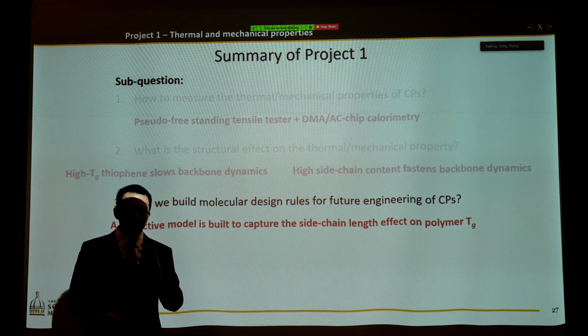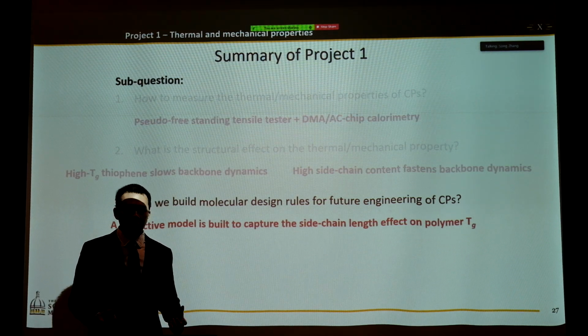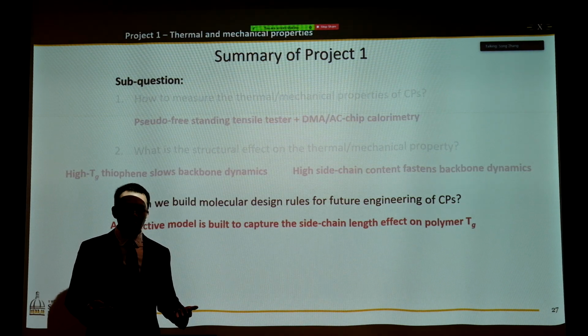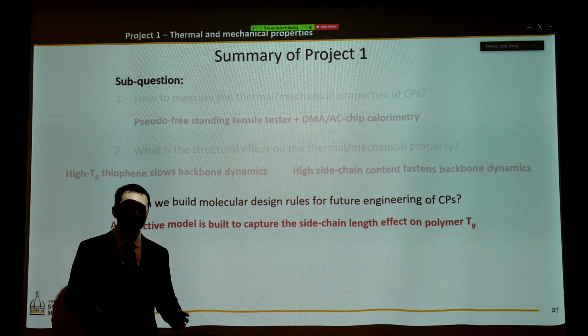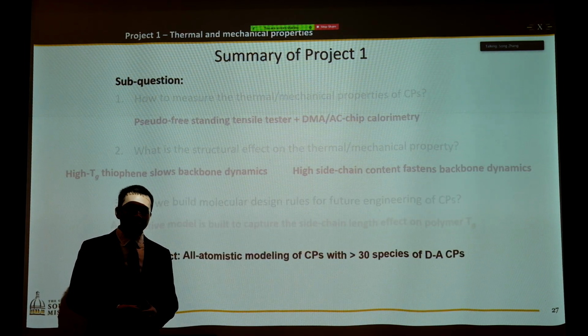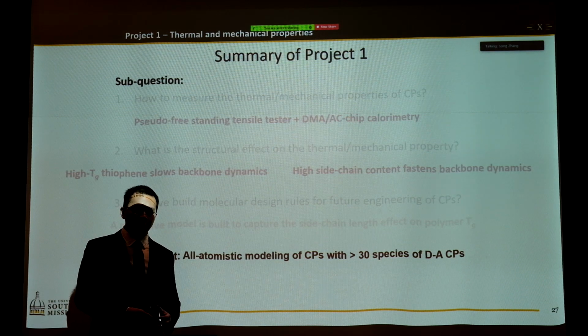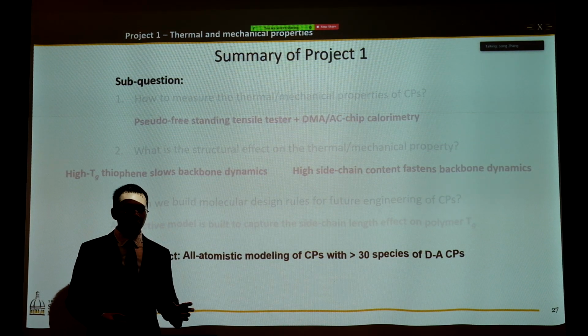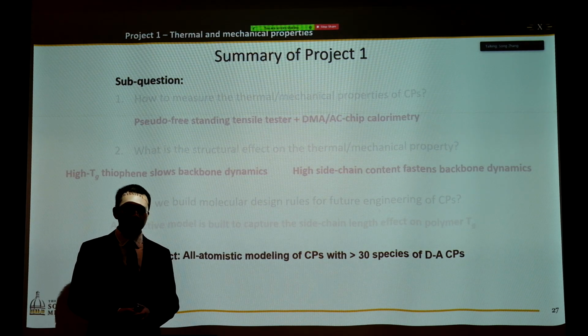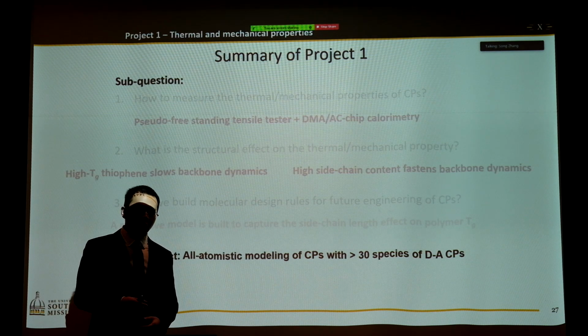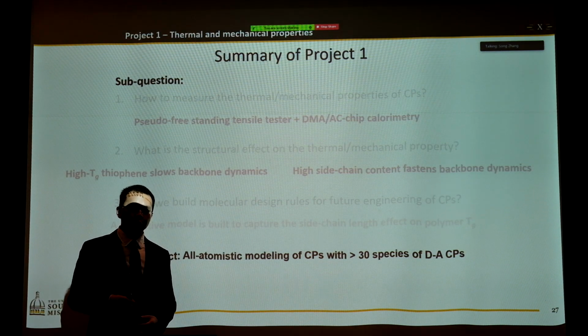We can simulate DPPT polymer, DPPT2 polymer. But for another polymer system with different polymer backbone, if we want to use this model, we might have to synthesize 4 or 5 polymer structures with different side chain length. And that is not efficient at all. Okay, how do we figure out that problem? Now we are collaborating with the simulation group and trying to combine the simulated result with our experimental measured result. And by using all atomistic modeling, we hope that in the future, if you draw a chemical structure on the paper, we will be able to tell you what's the Tg for that.